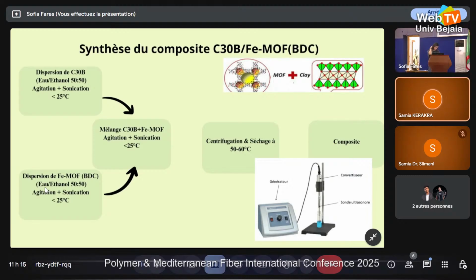Synthesis of the composites, MOF and clay. This protocol ensures good dispersion and possible physical-chemical interaction between the two fillers, even without coupling agents. First, we disperse the clay in a water and ethanol mixture, stirred and sonicated below 25 degrees Celsius. The MOF was dispersed similarly under the same conditions. Then both solutions were added to each other, and the mixture was centrifuged to remove solvents, then dried at 50 degrees Celsius for 12 hours to obtain our composite powder. Next, please.